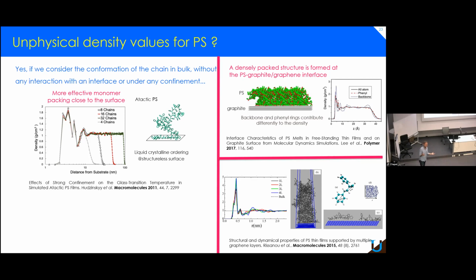But maybe you can help me. We are not opposed to the idea that density changes as a function of H. The trouble is also if it agrees that H enters in the calculated mass density. Suppose now that this density profile which I have measured is more or less abrupt. The definition of H might change, because depending on how you measure it, the tail of the distribution matters. So that's a discussion for after. If you have time, I can drop by. That would be interesting for me.